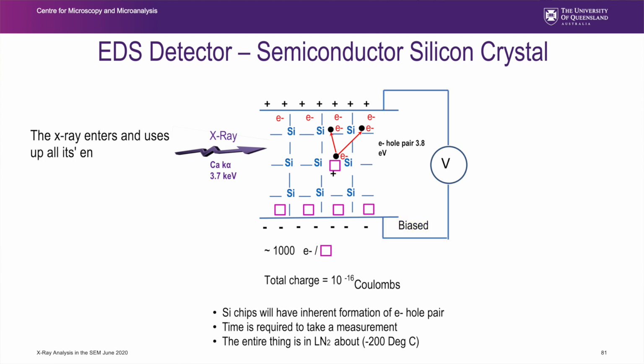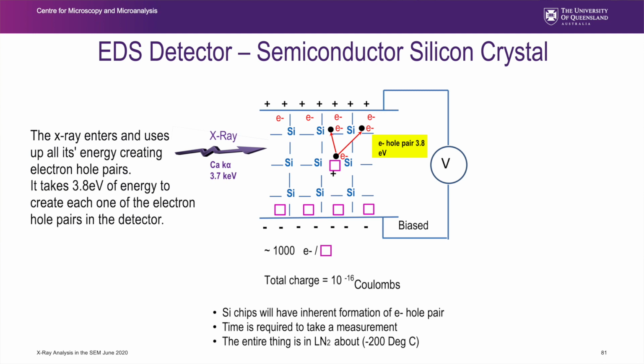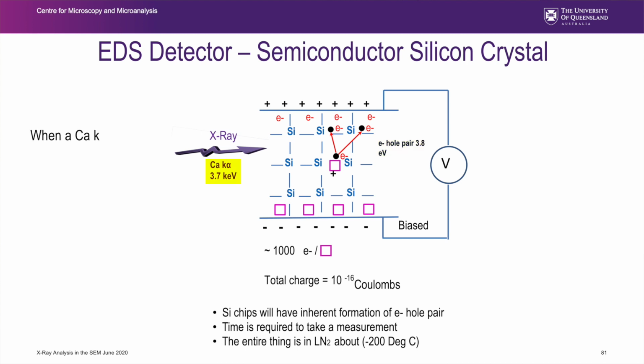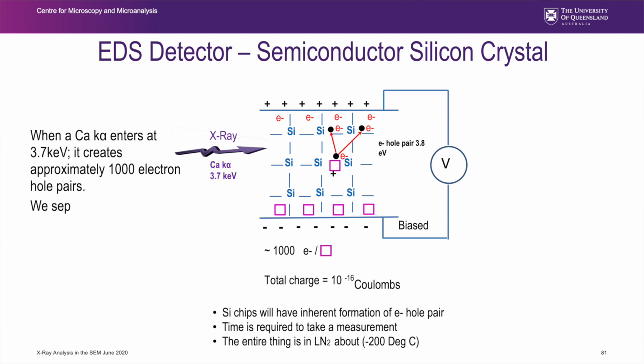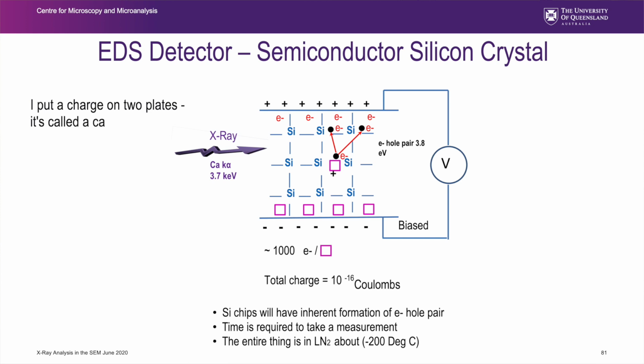The X-ray enters and it uses up all its energy creating electron hole pairs. We know that it takes 3.8 eV of energy to create each one of those electron hole pairs in my detector. So when a calcium K alpha enters at 3.7 keV, that creates roughly 1,000 electron hole pairs. And we separate them by having a bias on the plate.